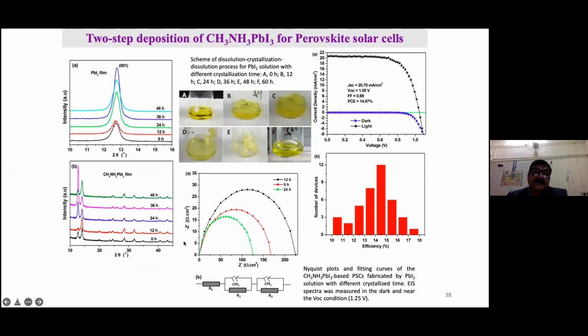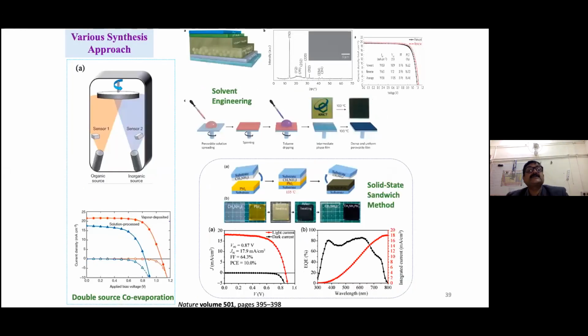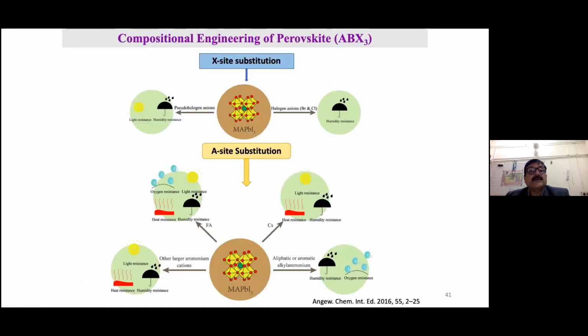These are the data showing the current values, with the number of devices, with the efficiency, because the main issue with these devices is durability. They are not stable. Sometimes they are stable for less than 1 day. So even if it shows very high efficiency, if it is not working for a longer time, it has no meaning actually. So different synthesis approaches have been adopted to keep this material more and more stable. These are the efforts.